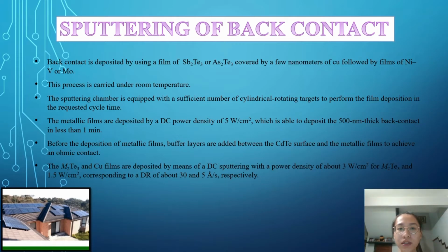The sputtering chamber is equipped with a sufficient number of cylindrical rotating targets to perform the film deposition. So in order to achieve a 500 nanometer thick back contact, the metallic films are deposited by a DC power density of 5 watt per centimeter square. Before the deposition of metallic films takes place, buffer layers are added between the cadmium telluride surface and the metallic films to achieve an ohmic contact.